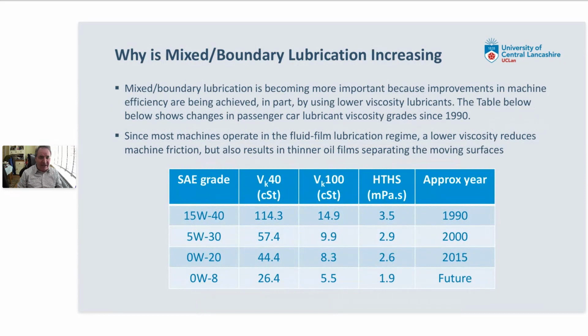And one reason why mixed and boundary lubrication is becoming more important is because there's an increase in interest in making machines more efficient. And one way of doing that is to use lower viscosity lubricants. So this table below shows how the viscosity of passenger car lubricants has changed since about 1990. So if we go to 1990, a lot of people were using SAE 15W40 grades in their engines, and these had the viscosities as shown in the table. So about 114 centistokes at 40 degrees C, or about 15 centistokes at 100 degrees C, and a high temperature, high shear viscosity, which is measured at 150 degrees C and a shear rate of 10 to the 6, of about 3.5. So that was the situation in 1990.